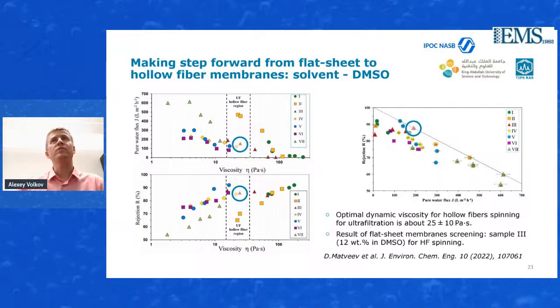And if you'd like to make a transition from the flat sheet to the hollow fibers, it's on the left hand side. So there are 2 graphs, and we mark the region of the viscosity which is quite optimal for the fabrication of hollow fiber membranes. And we can see here that based on the flat sheet membrane, we can also select quite a potentially good composition for the hollow fiber spinning. And we took the point on the right hand side, that is a composition that is already on the upper bound for the hollow fiber spinning.